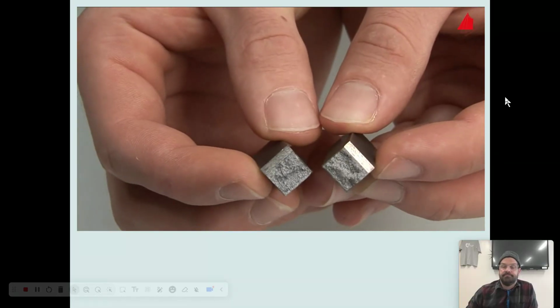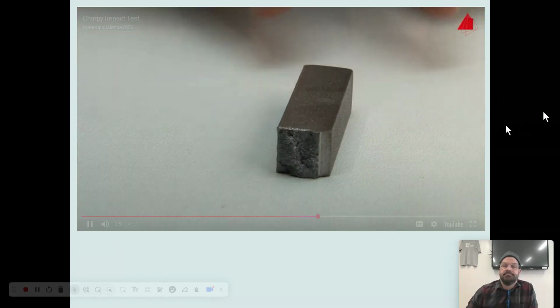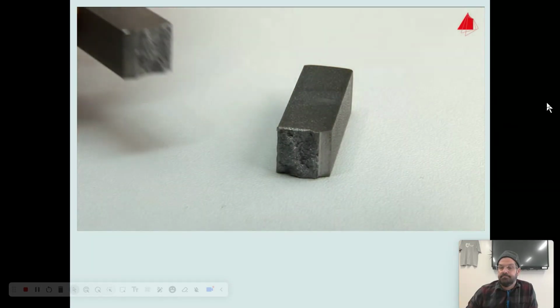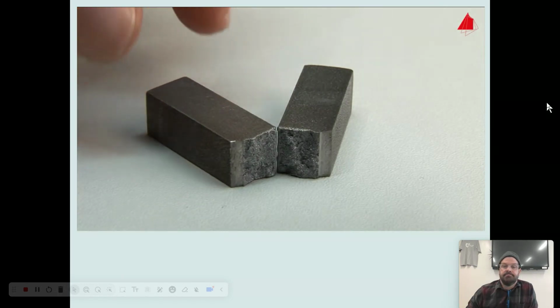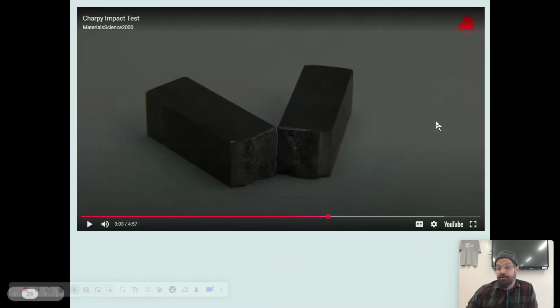This is another important indication that this kind of steel is only able to absorb small amounts of notch impact energy. It shows mainly brittle behavior due to the strain aging effect. Again, she used the word brittle. Brittle just means that it doesn't deform, it just breaks instead, fractures.